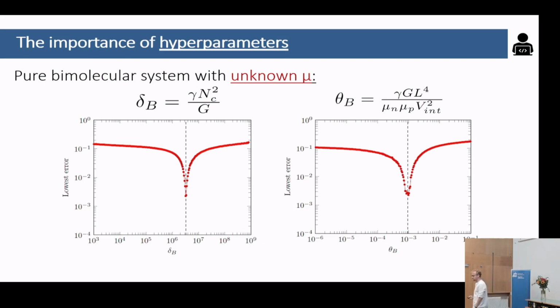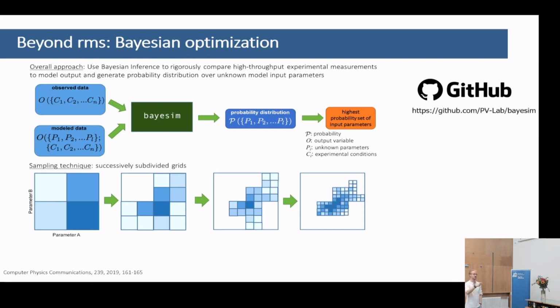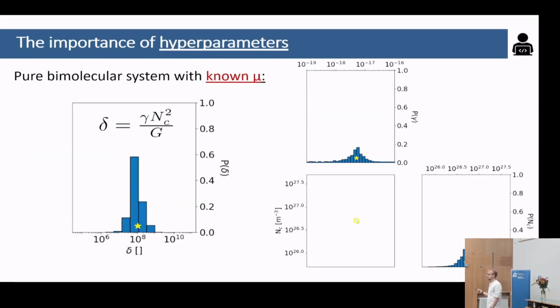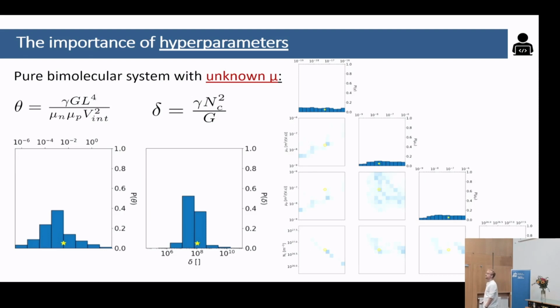And so this is nice, and you can also look at this in the same way that Thomas presented a couple of days ago, by using Bayesian optimization and Bayesian statistics. And you basically see a similar conclusion. If you have only 2-3 parameters and you know the mobility, you have a very narrow distribution on all of it, so you have a very well-defined solution. However, when you don't know the mobility, you see that it's somewhat flat for most of them. However, yet again, you see that you have a very defined distribution of what those figures of merit should be.